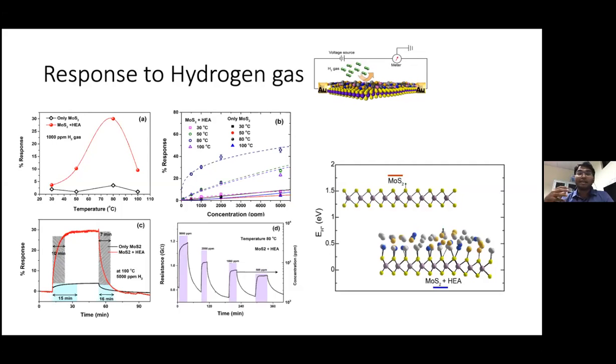You can see that the sample which had these particles, in effect, which had this Schottky barrier, was much more responsive to hydrogen. One of the reasons is, first of all, the catalytic effect of all these particles. They can be very good catalysts, and that can actually dissociate the hydrogen effectively, which leads to a spillover effect. On the other hand, one of the IISc collaborators did a DFT on this to calculate the adsorption energy of hydrogen on bare MoS2 and that of the MoS2 having these multi-component particles.